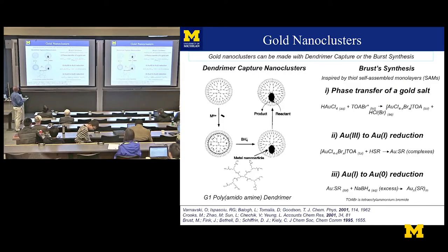There's been a couple of methods. The one is called the Brust synthesis, and it's a phase transfer of a gold salt. So you start with the gold salt, okay? And you add that, and then you have this gold 3 to 1 reduction. So you reduce that process, and then you have the gold 1 to gold 0 reduction. Finally, the excess is removed from the flask. You then actually mass spec these systems. You don't just look at them. You actually measure the mass spec, okay? And they have 25 atoms. You can follow this procedure.